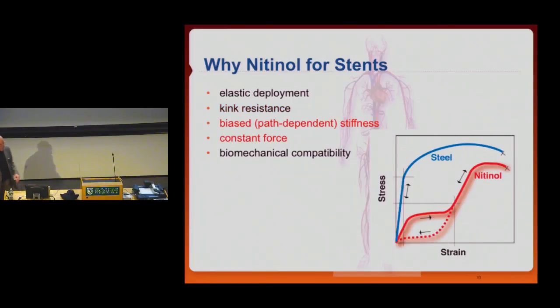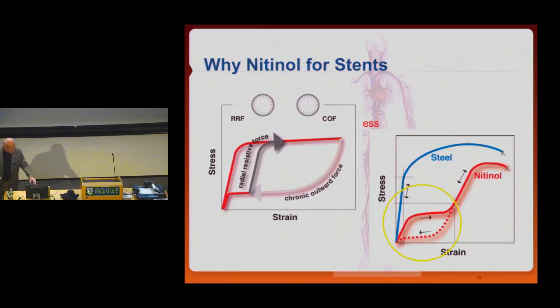Here's the most important aspect, which comes from this hysteresis in the stress-strain curve. We call that biased or path-dependent stiffness, meaning that this product is less stiff on unloading than it is on loading. What does that mean? If you look at this part of the stress-strain curve, when you superimpose these numbers here, stent diameter in this direction and hoop force, we can simulate the loading and unloading of a stent.